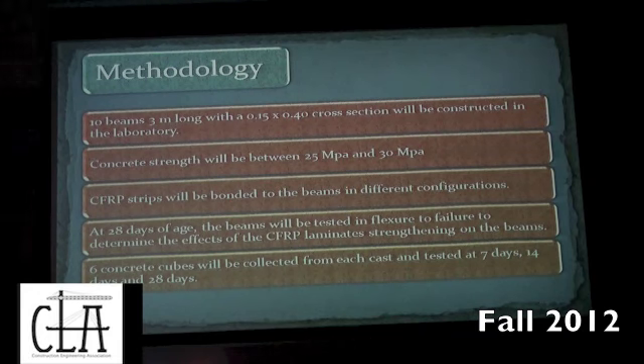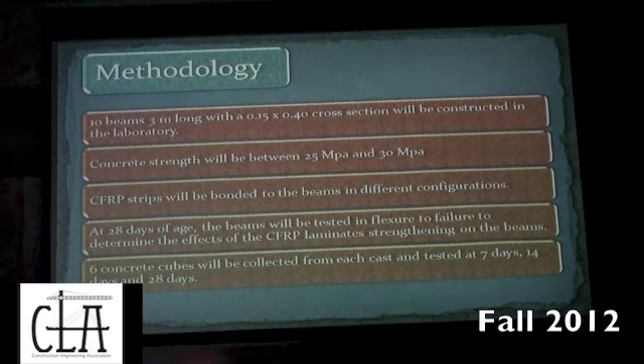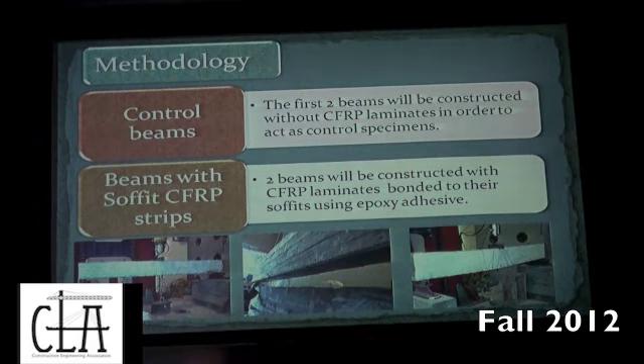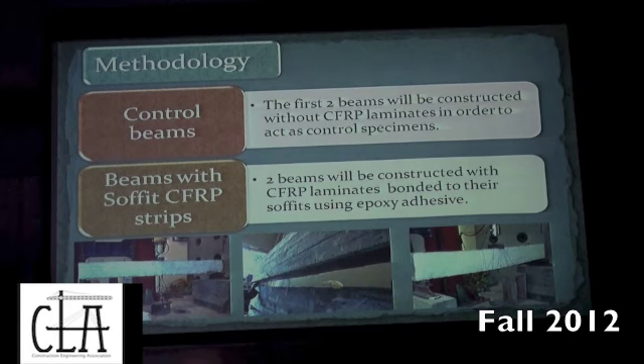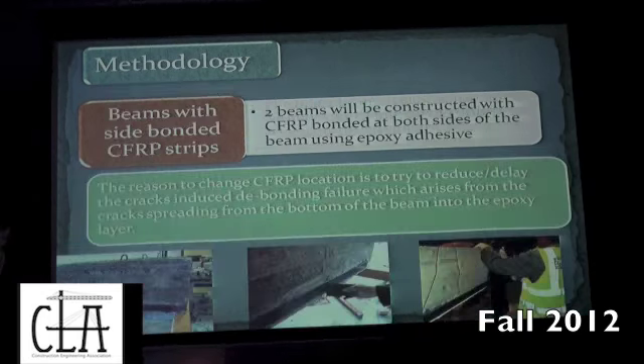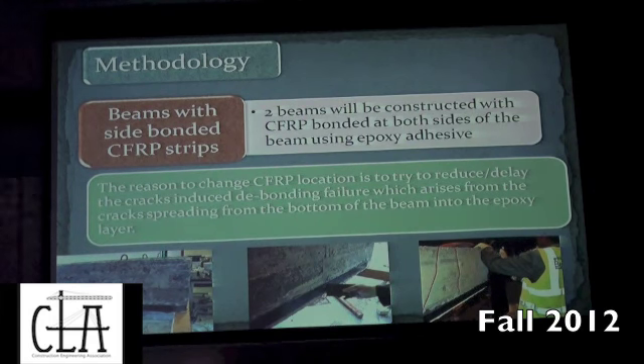And of course, for each cast that we do, we're going to do 6 concrete cubes, which should be tested after intervals of 7 days, 14 days, and 28 days. The first 2 beams that we're going to do are the control beams. Basically, they are without any CFRP laminates, and these are just acting as control specimens for the rest. The second 2 beams have CFRP strips at the bottom of the beams, and we're going to bond them using epoxy adhesive. And Muhammad will continue with that.